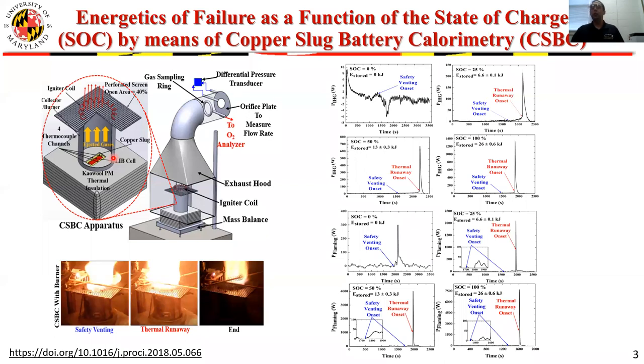And the challenge that we encountered very quickly was that it was fairly easy to ignite those materials with an external igniter and measure heat due to flaming combustion of the materials through traditional fire protection engineering means of oxygen consumption. But each time the cell would reach thermal runaway, the ejection rate would become so high that the flame would be automatically blown off. And that's not something that necessarily will happen in every particular situation. So we felt that it was important to capture the total combustion energy of these ejected products. So we added this cup assembly to our calorimeter to be able to slow down the gaseous products ejected from the cells and direct them toward the hot wire igniter. That created a nice and steady flame.